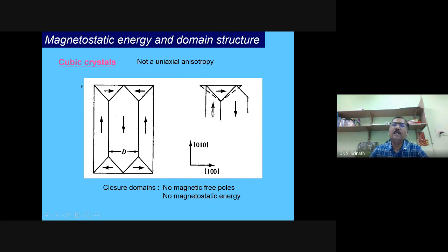Because on one hand, this domain is trying to grow this way. On the other hand, this domain is trying to grow this way. So because of that, there is a magnetostriction, and also arising because of that, there is a strain in the material. This strain can be minimized if we have a particular variation in which the domains are oriented longer. It can be in this direction, or I can rotate by 90 degrees and say that horizontal is longer than the vertical. It's only the way in which you look at it, doesn't matter.